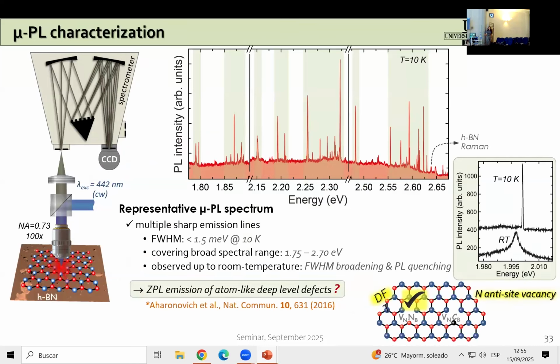So in the case of hBN flakes, which are transferred onto a silicon dioxide substrate here, using the same confocal micro-PL setup, we observe at low temperature such a PL spectrum. And as you can see, there are many sharp and intense lines here, and they span a very broad range from some 450 or even below nanometers to some 700 nanometers. Now, the line width of these peaks is around 1.5 milli-electron volts at low temperature. And some of these lines are observed even at room temperature, with, of course, expected PL quenching and line width broadening.